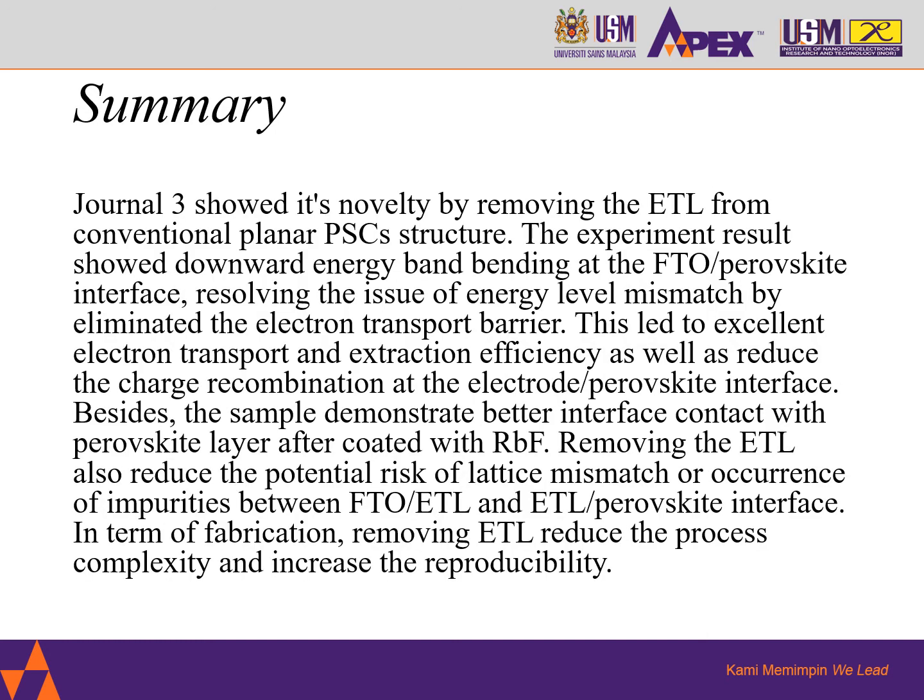After looking into all the comparisons, journal 3 showed the best novelty by removing the ETL from the conventional planar PSC structure. The experimental result is very promising, where they are able to demonstrate a downward energy band bending at the FTO perovskite interface and totally remove the electron transport barrier. So this resolved the issue of energy level mismatch encountered by other conventional planar PSCs.